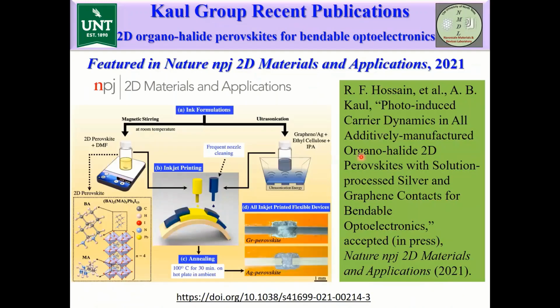Now, the study that I'm going to present is published in npj 2D Materials and Applications from our group. In this work, we have done fully inkjet printing of perovskite ink on a polyimide flexible substrate, and the top electrical contacts, metal contacts, were also inkjet printed, which are graphene and silver.